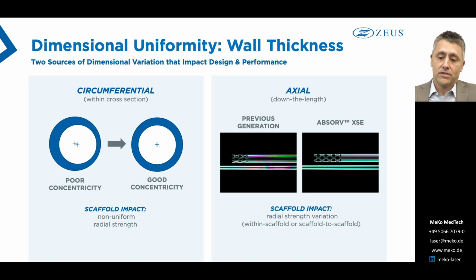So one of the main aspects of uniformity is dimensional uniformity, with most other aspects, such as mechanical property uniformity, really extending from there. So for tubing that's to be converted to a BRS, it's the wall thickness uniformity that's the most important, as there's a direct correlation with strut thickness in the BRS and the wall thickness of the tubing. Wall thickness variation, or we could call it non-uniformity, can rear its ugly head in two ways, either within cross-section or down the length, or axial, so circumferential or axial.